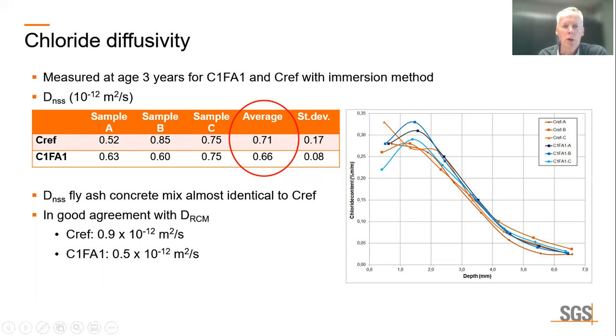In this table, we show the results, and we can see that both concrete mixes have a chloride diffusivity of 0.7. It's almost identical, certainly if you take into account the standard deviation.